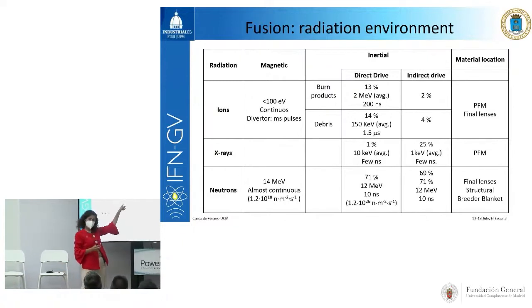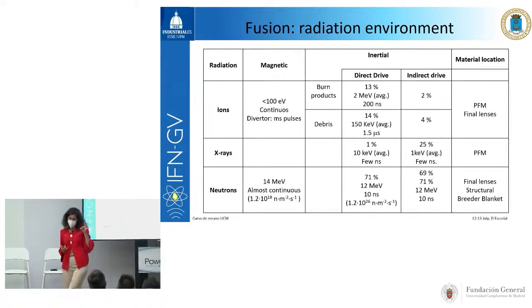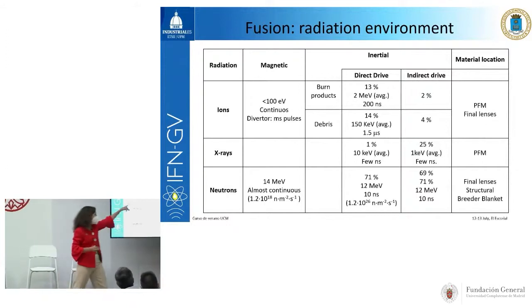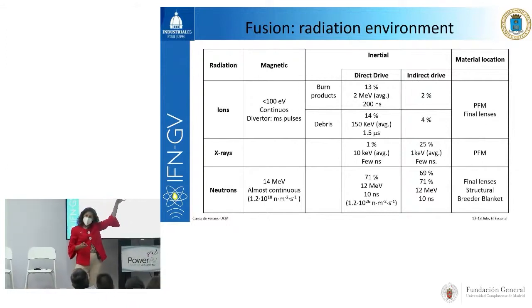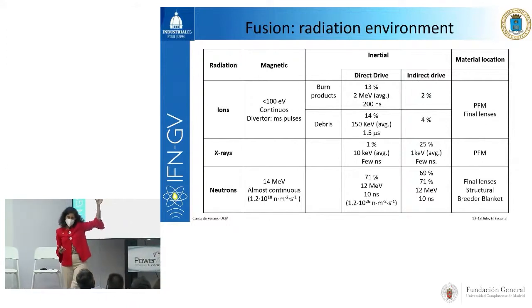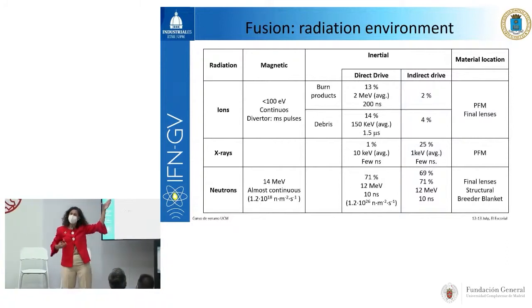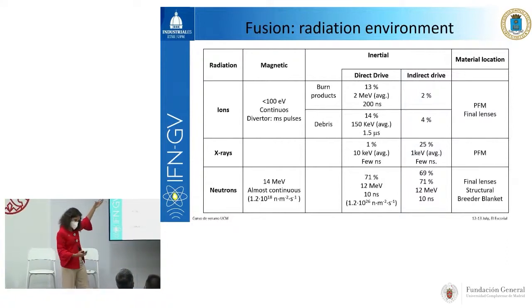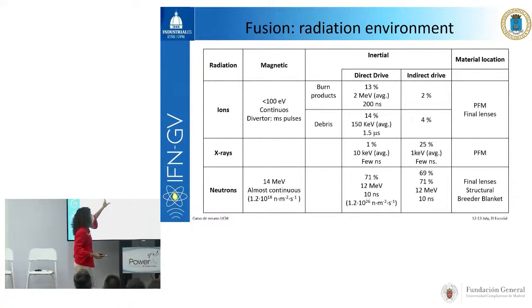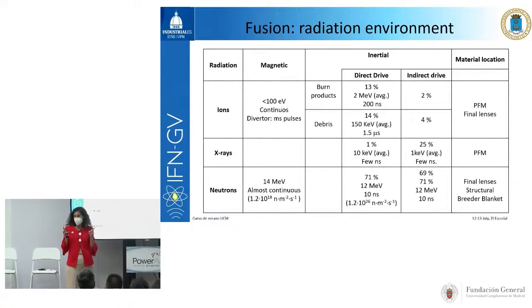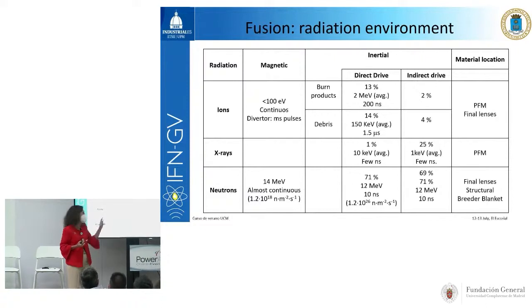If we are dealing with magnetic fusion, we are going to have low energy ions. Sometimes the energy of these low energy ions is below the so-called displacement damage threshold, okay? But they are still going to produce damage because of other factors, okay? And in general, the irradiation is going to be continuous, with the exception of the divertor, okay? In the divertor, we are going to receive pulses because of the plasma inhomogeneities.